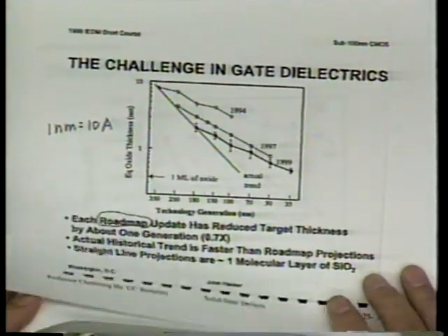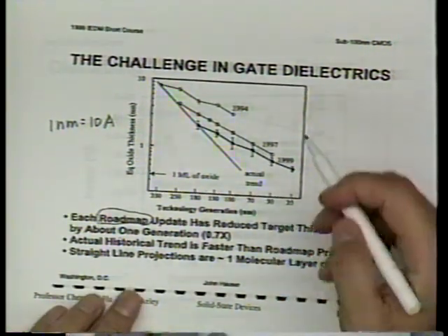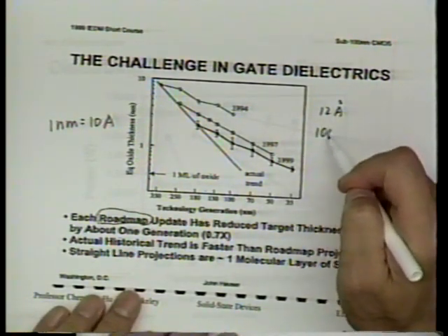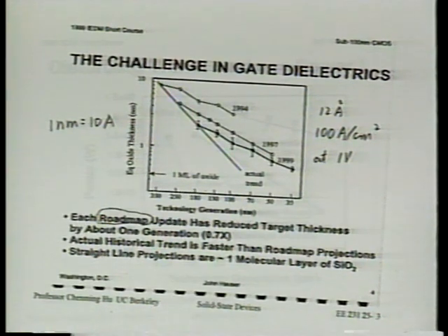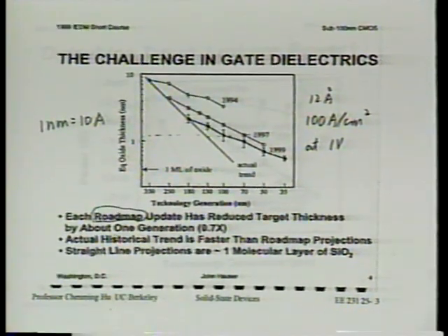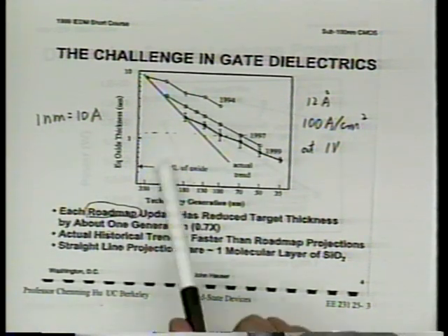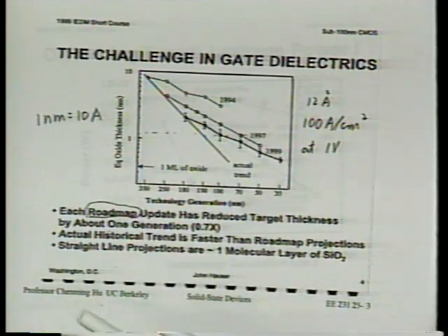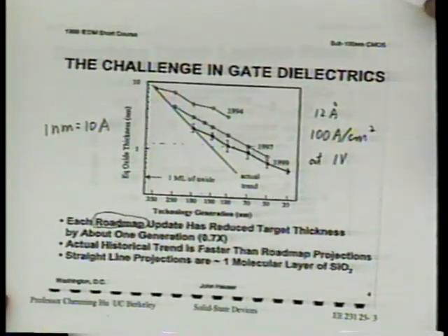With silicon nitride, the equivalent thickness might be pushed from 12 to about 8 Angstroms. In manufacturing today, no one has yet gone to 8 Angstroms in production; 15 Angstroms is common, gradually creeping toward 12. The exact point where high-k beyond silicon nitride becomes necessary depends on application — DRAM and low-power handheld devices cannot tolerate as much leakage as high-speed desktop applications.